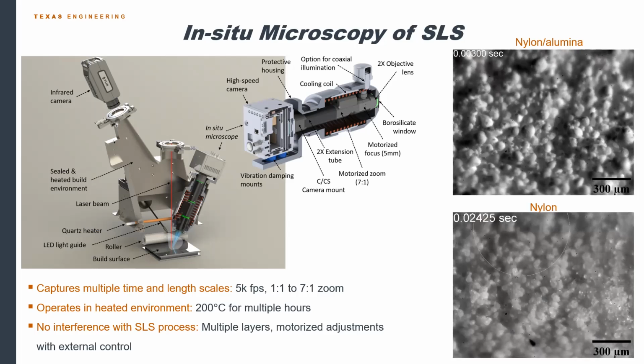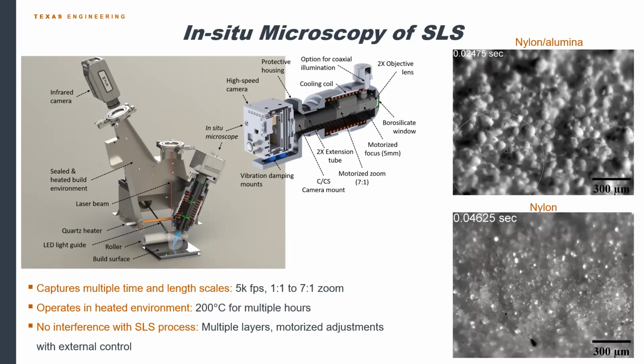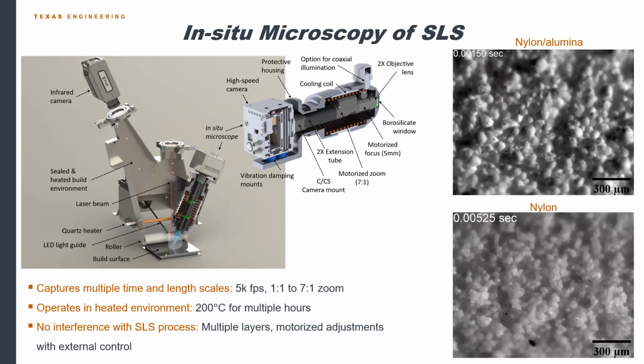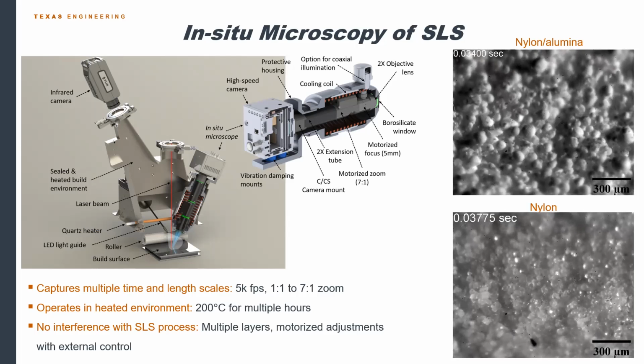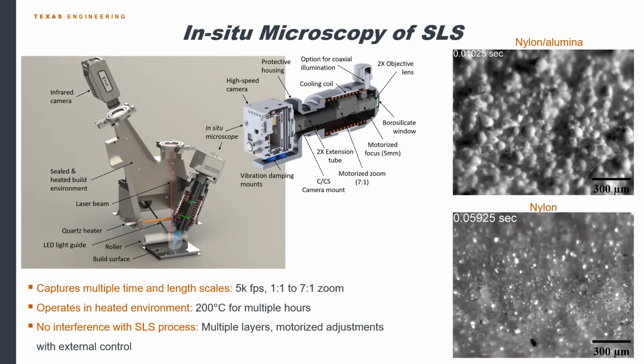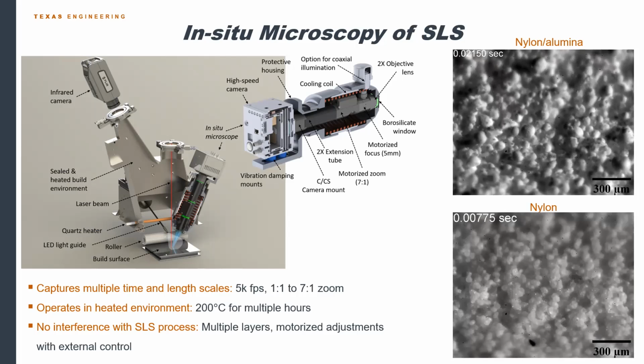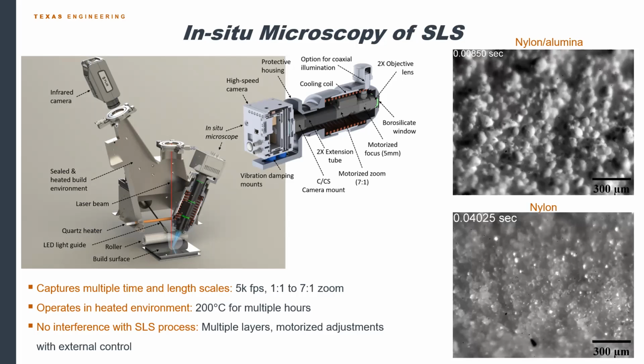So just real quick, in terms of the capabilities of the device, it can span the time and length scales of the SLS process. For example, you need to capture the particle scale dynamics, which are very fast, very small. You also need to capture the powder bed dynamics, which are a little bit larger and a little bit slower. So with this instrument, you can adjust those two parameters. It can also operate under realistic manufacturing conditions, so it can operate in a heated chamber. You can image multiple layers because it clears the powder deposition system. And all of the adjustments are external, so the machine can stay sealed the entire time.